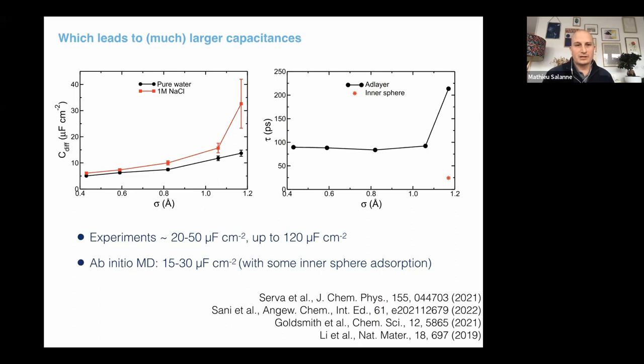Then again, we looked at the impact on the capacitance, and you see that when you increase the Gaussian width, so when you go more and more metallic, you have a large variation of the capacitance, in particular in the presence of sodium chloride, because you switch from a value of 5 microfarads per square centimeter to something like 30. And we tried also another point with an even larger Gaussian, but then the capacitance can reach 100 or 150 microfarads per square centimeter, but the time scale of the adsorption starts to be very, very long, longer than even 10 or 15 nanoseconds. So we don't have enough statistics to be sure of this data.